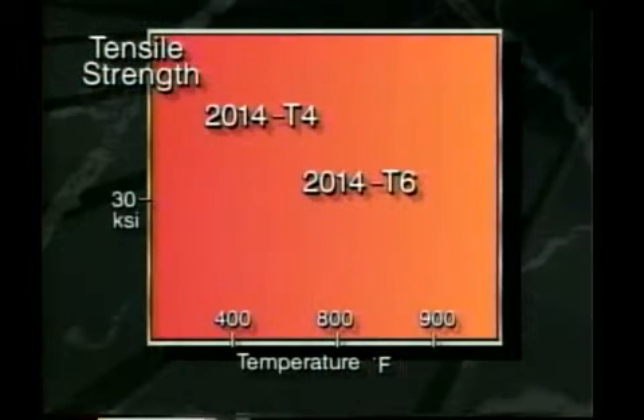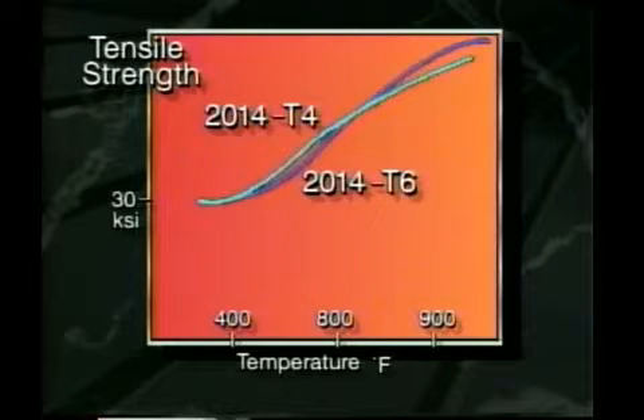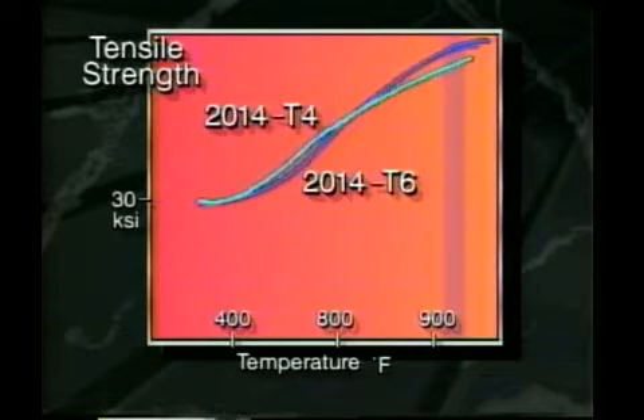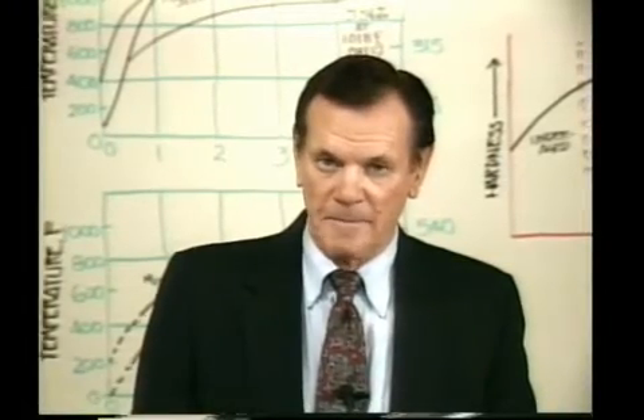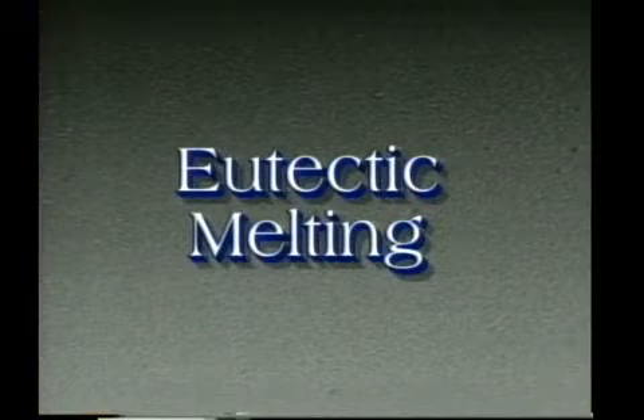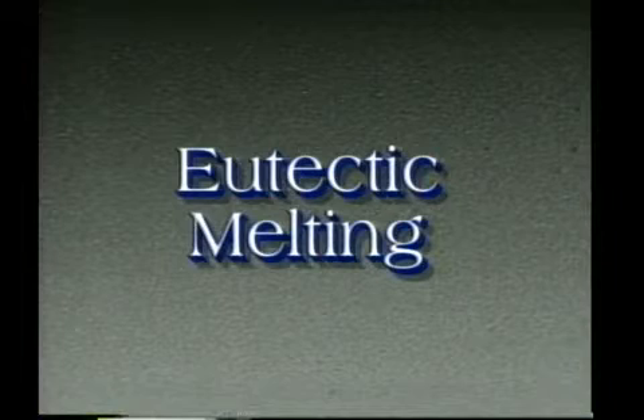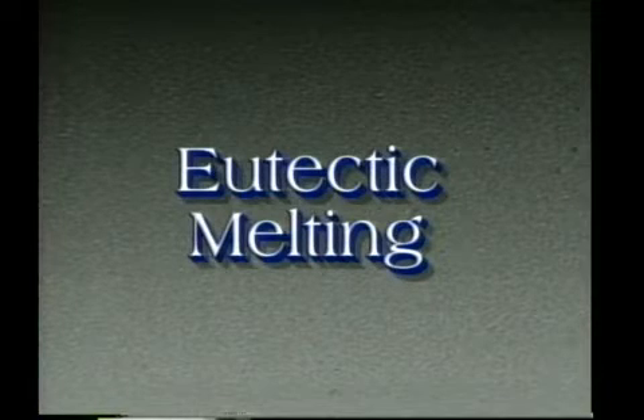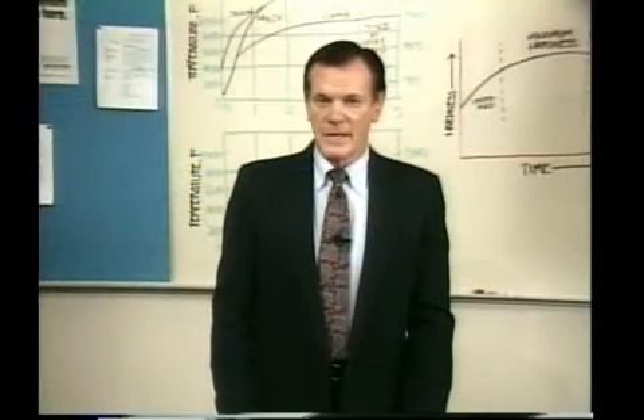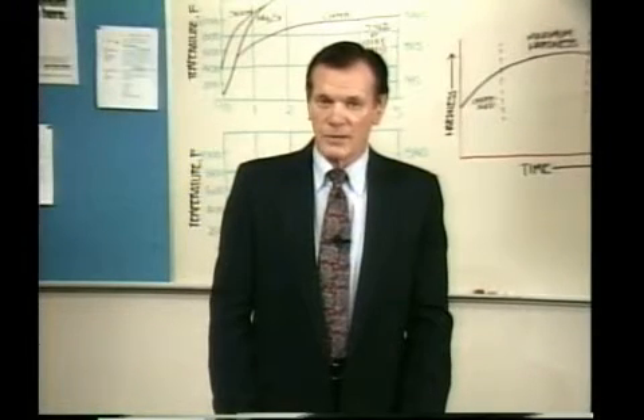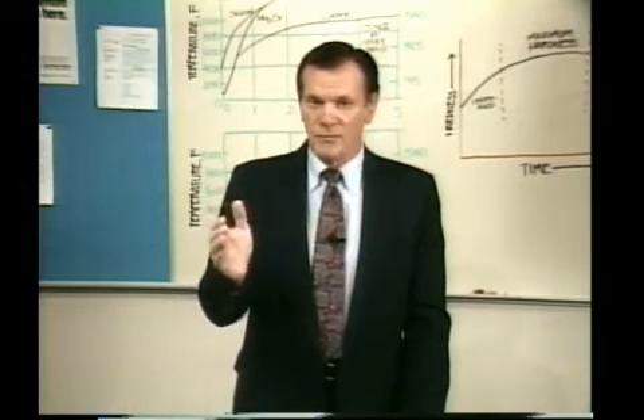This graph shows the effect of the solution heat treating temperature on the tensile properties of 2014 T4 and 2014 T6 sheet material. The maximum strengths occur just below the eutectic melting temperature of 955 degrees. Most high-strength 2000 and 7000 series heat-treatable aluminum alloys behave in a similar manner. As we have observed for most heat-treatable aluminum alloys, the maximum amount that can be dissolved occurs just below the eutectic temperature. The eutectic temperature is that temperature at which actual melting of certain particles starts to occur when the part is reheated for any reason.